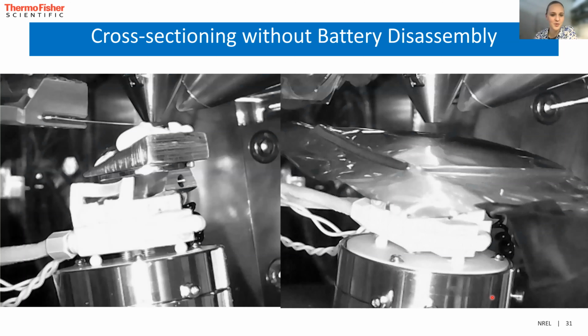Okay, so here's an example of what it looks like. We used a wedge to get a higher angle of the electrode stack inside the plasma FIB. Then we have a shutter that comes down to protect the SEM column from the laser, because there's a lot of ablation that occurs, and that shields the SEM column. We did try pouch cells, but unfortunately the thermal mass of the pouch cell did not stay cool, and for liquid electrolytes that's not a good plan because they heat up very quickly. On this stage, where most of our imaging was done, the stage was held at about negative 110 degrees C. Some of the newer stages can go closer to liquid nitrogen temperature, but this is where we were.